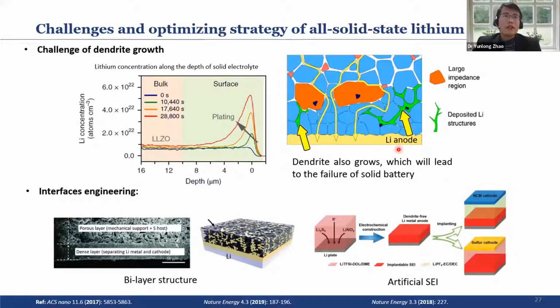So also with interface engineering, there are a lot of strategies to overcome these issues. For example, we can introduce artificial layers, an artificial SEI, or additional layers that allow lithium-ion diffusion but stop the electrons from penetrating. That could be very useful to avoid this kind of situation.